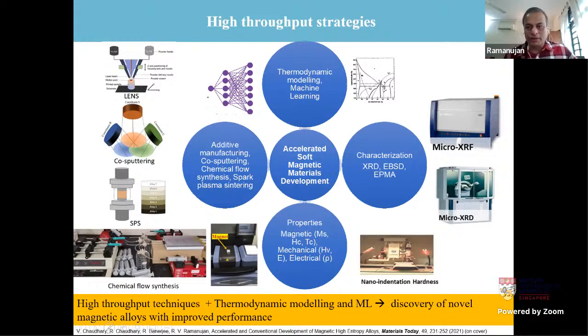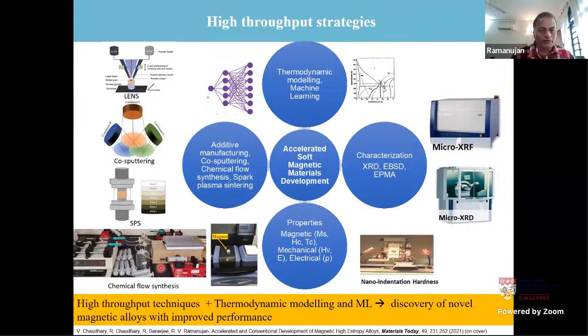We used 3 experimental techniques. One is LENS, which is an additive manufacturing technique. The second is using spark plasma sintering of powders to produce a graded sample. And the third technique is chemical flow synthesis, which we use for preparing samples. Right, so we use 3 different techniques: the LENS technique, the SPS, spark plasma sintering technique, and the chemical flow synthesis technique. We also use different characterization tools in order to accelerate these processes. Okay, so let's get started with the high throughput additive manufacturing approach.